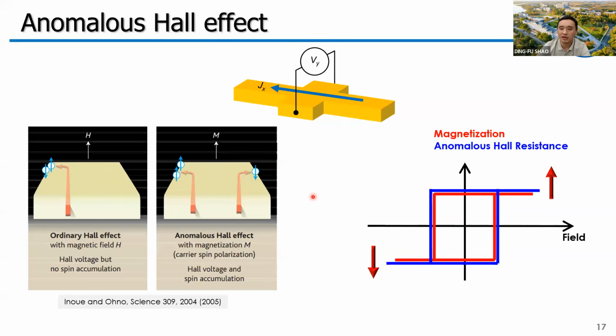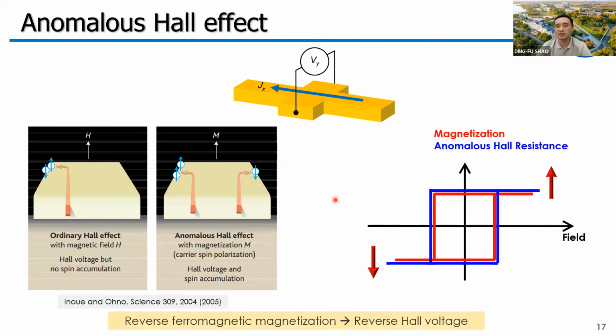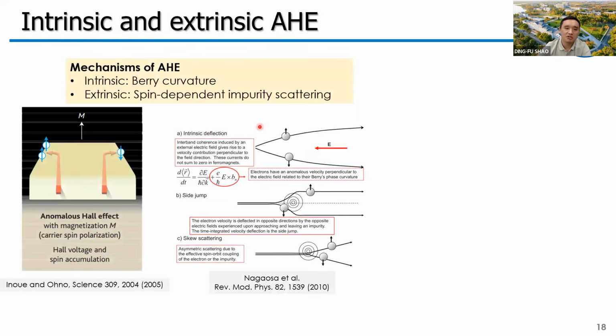Anomalous Hall effect is an intrinsic property of ferromagnetic metals, and the Hall current direction is strongly dependent on the magnetization direction. So this effect is widely used to detect the ferromagnetic order parameter. The anomalous Hall effect can be introduced intrinsically by Berry curvature or extrinsically by some impurity scattering.